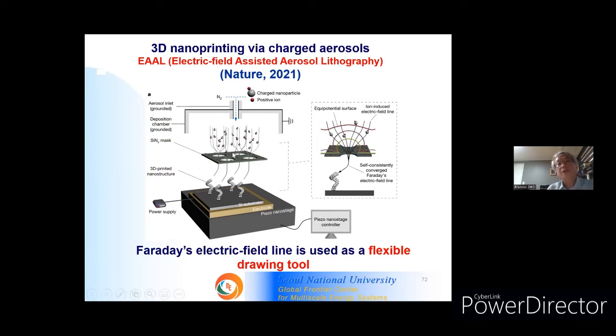Of course, even when we float this dielectric silicon nitride mask, ion deposition on the mask surface generates an electrostatic lens, and the electric field is focused. The charged particle just follows this electric field, and the substrate is moved in 3D dimension using a 3D piezo nanostage to make versatile kinds of three-dimensional nanostructures as you wish. So this might be regarded as a real 3D nanoprinting technique using aerosol technology.